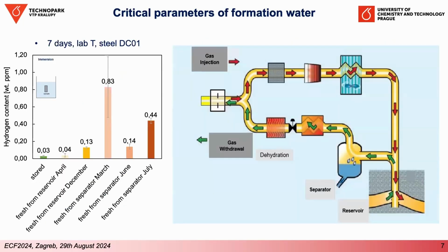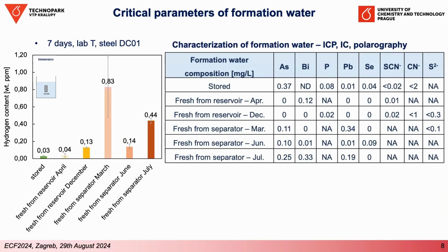So we approached a sampling step of these formation waters directly from different parts of the reservoirs where the formation water is typically present. And it was quite surprising for us that it can differ really significantly, because at the beginning we worked just with the stored samples. There was some hydrogen uptake, but not so dramatic. But when we did some testing with the fresh samples, there were quite high differences between these samples. And we did a lot of characterization of these samples.